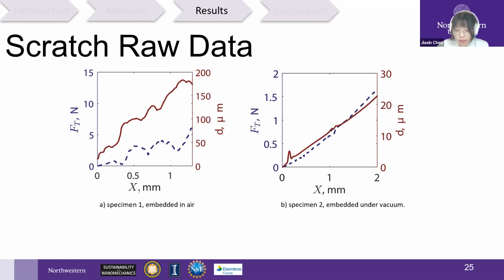In contrast, we used a maximum vertical force of 2 Newton for the vacuum embedded specimen. During epoxy embedding and the vacuum, the resin is pushed into the microscopic pores due to the vacuum. Unfortunately, this results in a composite structure at microscopic level consisting of the resin and the ASR gel. Therefore, we purposely selected a lower force to obtain a depth of testing in the microscopic range. The maximum penetration depth in this test was 28 micrometer, as shown in the right-hand side figure. The scratch length was 2 mm for both specimens.